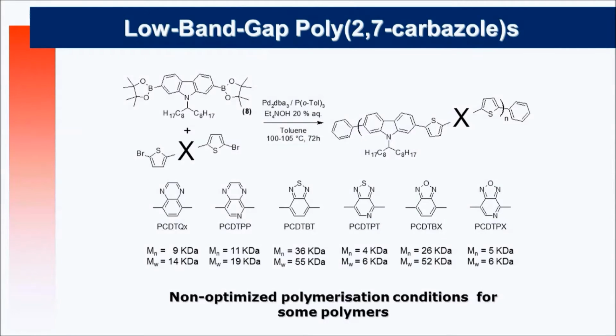So he started with this carbazole here, and the key point, I removed this slide, but the key point, you don't start from carbazole, you start from a biphenyl unit and you make a ring closure. And therefore you get access to the carbazole unit. And with this boronic ester derivative here and with any dibromo aromatic groups, you can make different copolymers and fine-tune the band gap and optimize the optical properties and the electronic properties.